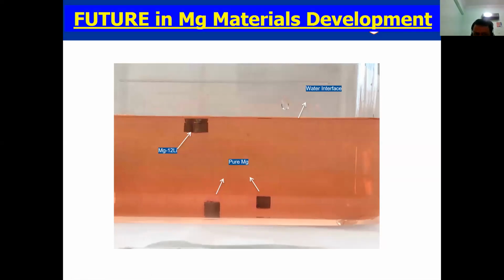We are also trying to develop very lightweight, I will say ultra lightweight, magnesium-based material, which can float in water. So you throw it in the water, it will float there. You can see this, for example, by putting lithium in there, this piece is floating, while the pure magnesium is settling at the bottom. So we have reached this level and we are further improving on that.